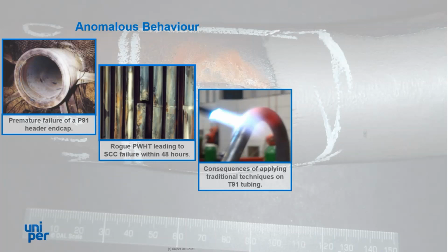And in issues where the contractor's not necessarily got the fabrication quite right and sought to correct their errors through the application of techniques used by the materials of yesteryear, such as the T11, T22, you can get marked changes in the microstructure, which once again will either lead to premature failure through creep or other damage mechanisms like stress corrosion cracking. The example shown here is also worth noting that a cherry red in a component isn't necessarily the same in a well-lit workshop as it is in a dull workshop.